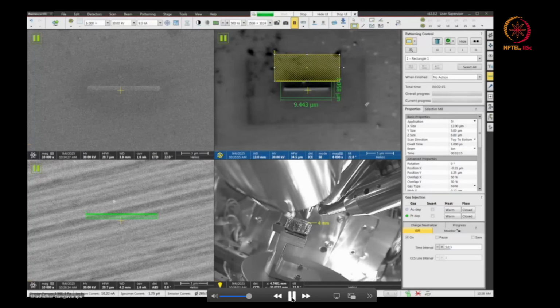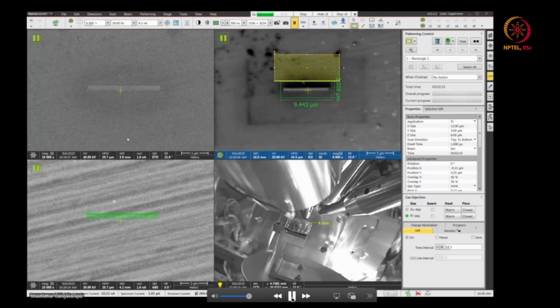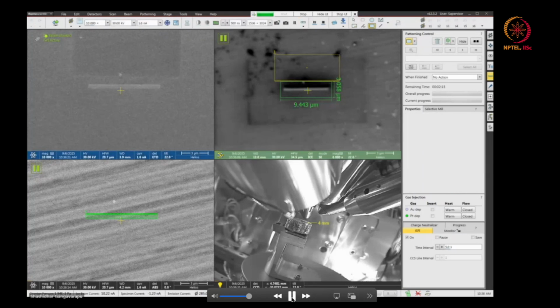So now I set the pattern perfect position, and I can start this patterning. Basically, the gallium ion removes material from this pattern region. So it will take at least 2 minutes. Now you can see in the E-beam window, my material is basically removing. The high energy gallium ion is sputtering atoms.